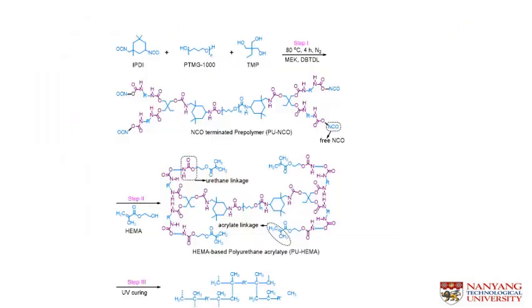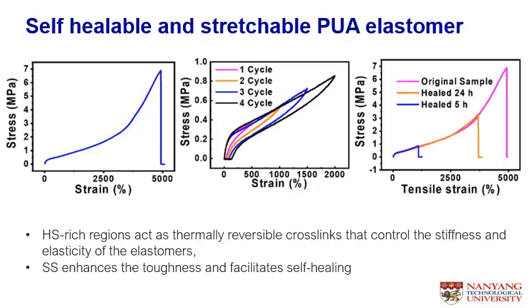The synthesis of the material is shown here, where an NCO-terminated prepolymer is prepared, followed by the grafting with HEMA group, realizing a HEMA-based polyurethane acrylate material after UV curing. The resultant material has abundance of hard segment-rich region that serves as thermally reversible cross-links that control the stiffness and elasticity of the elastomer. Meanwhile, the soft segment enhances the toughness and facilitates the self-healing.